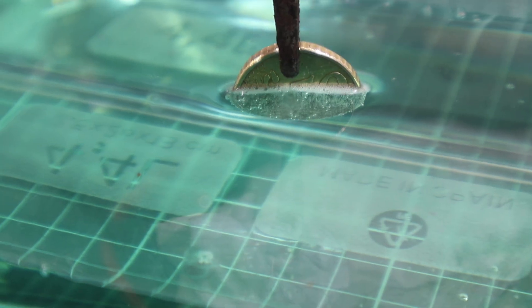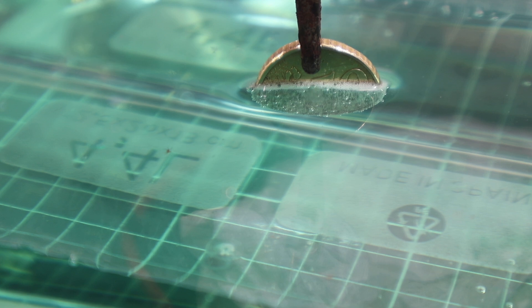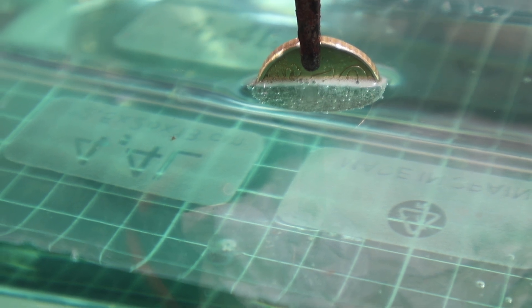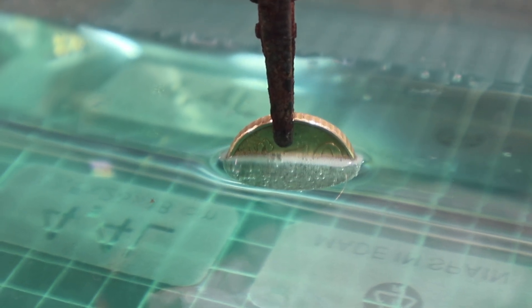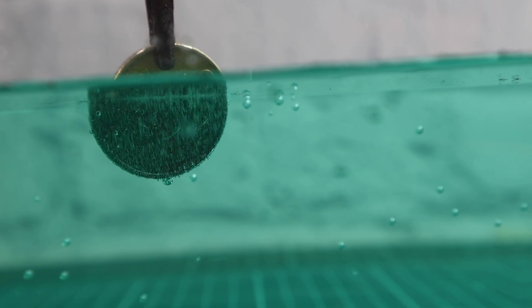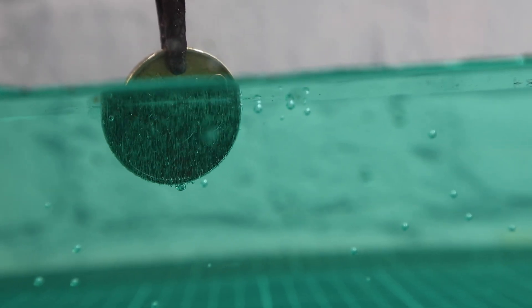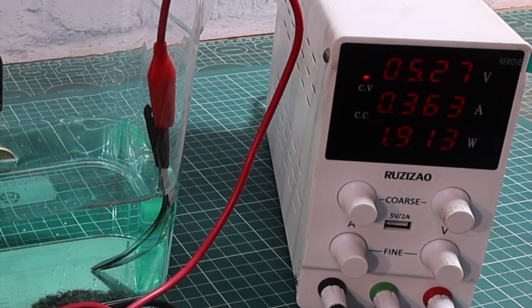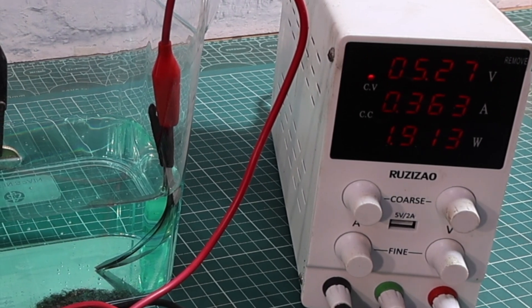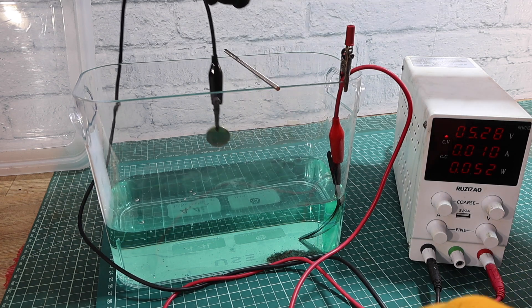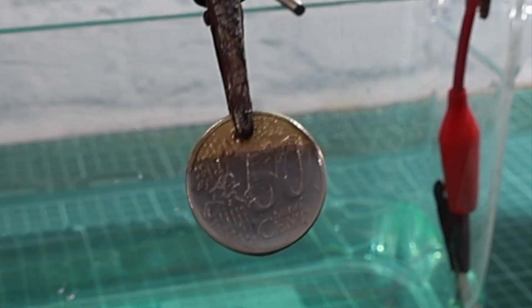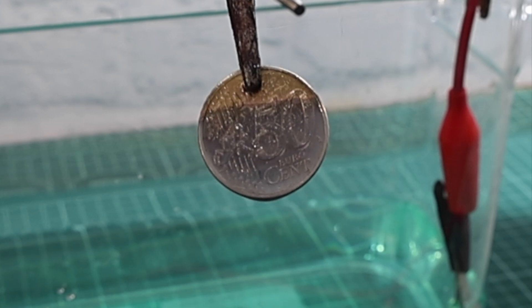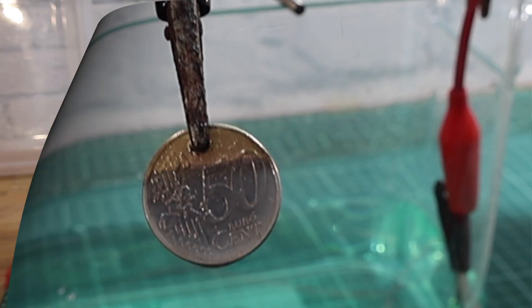And we can see the bubbles again. So this is basically attracting the nickel inside this solution. We're plating with five volts and 0.3 of an amp. There's another shot there. You can actually see it changing color. This is very quick. I mean, all of this electroplating, I did it all in the time that it took me to drink a mug of tea, more or less. So now we can see the line there where it's been nickel plated. That's only probably about five minutes, something like that.